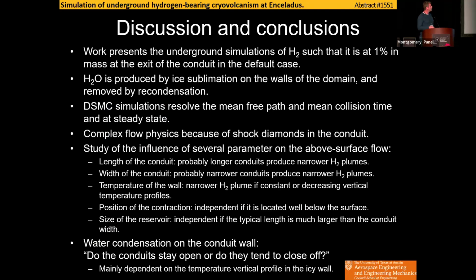Which takes me to the discussion and conclusion. So I presented here a direct simulation Monte Carlo of H2 and H2O, H2 being fluxed in the problem from the bottom, H2O being evaporated and sublimated from the walls and also being able to condense on the walls. The DSMC simulations are resolving the mean free path and the mean collision time, have enough numerical particles, and are all presented at steady state. You saw that we have a complex flow physics because of the presence of all the shock diamonds in the conduit. We studied the influence of several parameters listed here.